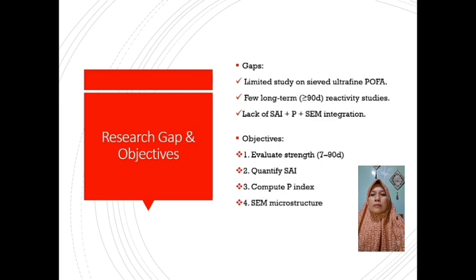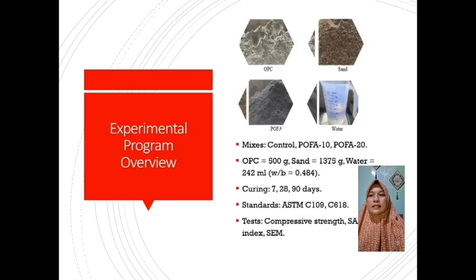Mortar mixes were prepared with ordinary Portland cement, natural sand, and sieved POFA. The mix design consists of 500 grams of binder, ordinary Portland cement, 1,375 grams of sand, and 242 milliliters of water, giving a water binder ratio of 0.484.